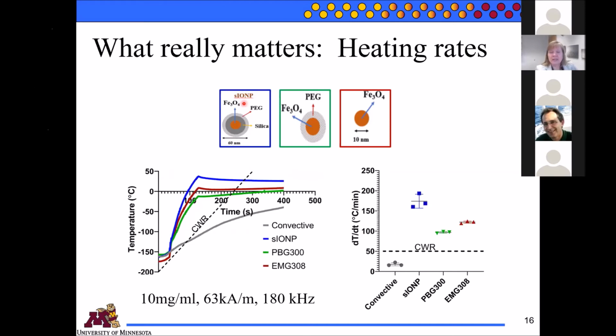Right, so heating is what really matters. The SLP is a nice way to compare particles, but when you actually put the nanoparticles in a cryopreservation agent, how well do they heat the sample? And they have to heat faster than this critical warming rate that I mentioned earlier. So convective heating doesn't do the job. The sample will crystallize on warming, guaranteed, and probably crack as well because the convective heating is going to heat the outside of the organ faster than the inside.